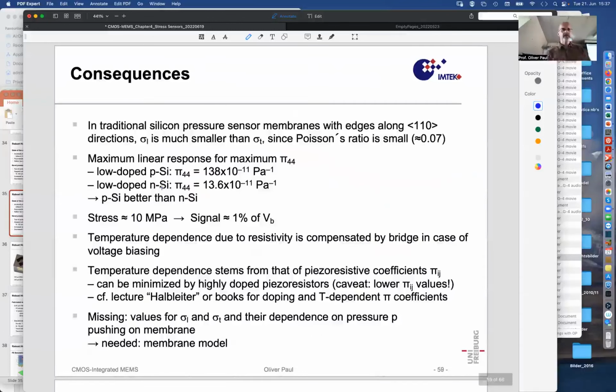So what we need is actually a model of the membrane. But before that, let me just summarize a few consequences here. In these traditional silicon pressure sensors that are still sold by the millions for all kinds of measurement purposes, those have these anisotropically etched edges along 1,1,0 directions, and then sigma L is much smaller than sigma T because of Poisson's ratio. And then we need pi 4,4 to be large, and therefore we take P resistors, because pi 4,4 is larger than in N material. P silicon will be much better than N silicon for those resistors.